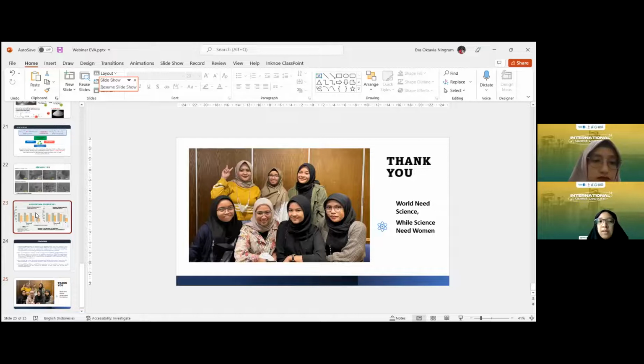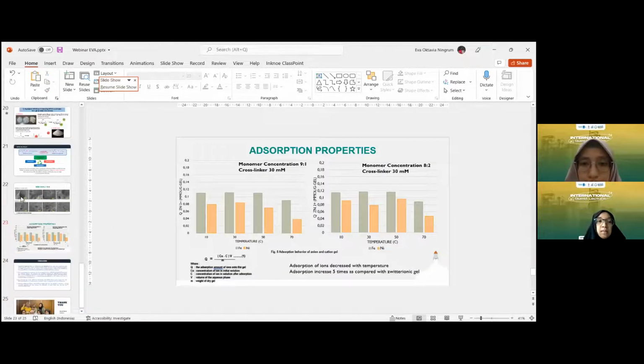Actually, from the absorption properties, it reached up to 0.1 millimole per gram gels. If we compare to other adsorbents, the polyNIPAM, the absorption capacity reached 185.3. I believe that with copolymer blending anionic and cationic, the absorption capacity must be higher than this value. The highest value of the adsorbent, especially for chrome ion, is from the zirconium loaded with monomer composites. The absorption capacity is around 172. So I believe that the blending between anion and cation becomes the promising adsorbent, which shows the higher absorption capacity.